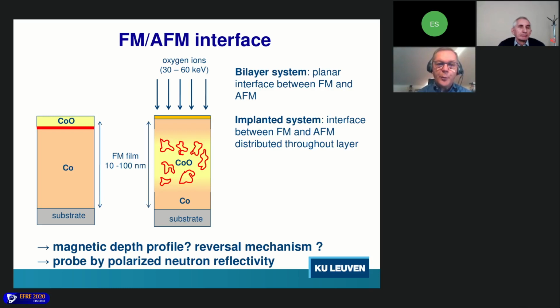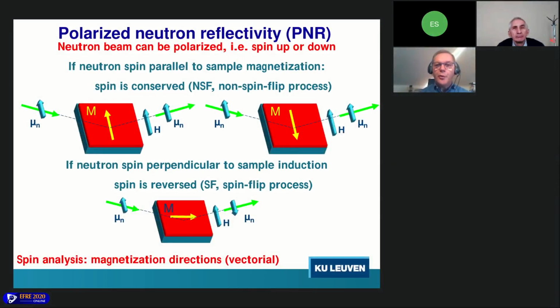And I will say a few words about that. In polarized neutron reflectivity, you do essentially the same as in X-ray reflectivity. So you measure the chemical depth profile of the layer, but when you use polarized neutrons, then you can also get information about the magnetism. In particular, what you need to do is you have to use a beam of neutrons that is polarized either up or down, and you have to measure again the polarization of the neutrons after reflection from the film.